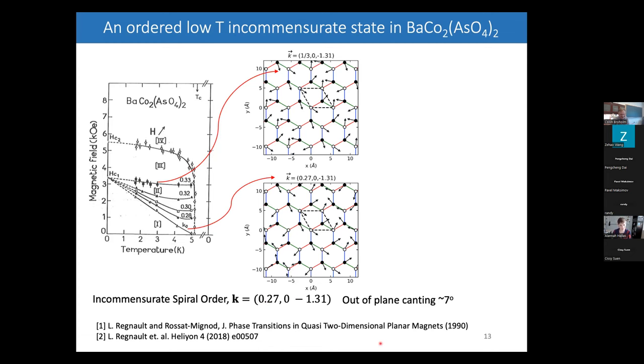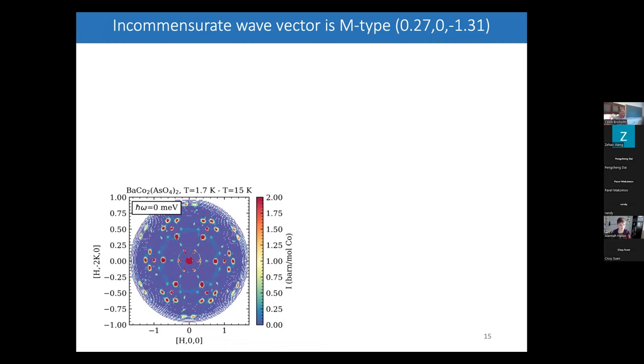I can't give you... it's a good question. I can't give you a back of the envelope explanation for why these particular two peaks are weaker than the others, but that is part of a fingerprint of that particular spin structure. And really, to determine this kind of spin structure, you need to go out to larger Q to also have this arrangement of the six satellites out here, and they will have a different pattern of modulation between them. And so all of that is the normal way that we determine the ordered magnetic structures.